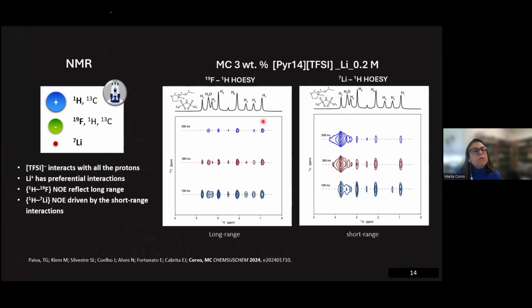And here you can see one of those experiments that is able to look at the relation between the different nuclei inside our gel polymer electrolytes in a spatial manner. What this means is that for these correlations, these spots that you see here, the bigger and more intense they are, the closer the nuclei are to each other. And these spots relate to the distance between fluorine and the protons in our cations. So bigger and more intense spots here mean that the fluorine nuclei are closer to this type of nuclei in the cations. And so here you can see that the cation is highly associated with the anion.